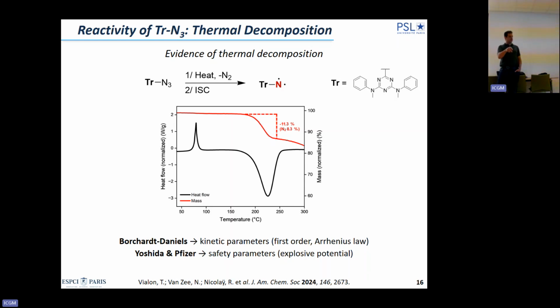And here, if you do this carefully, and this is well documented, has been done a lot, doing it at different temperature, different composition, you can access the kinetic parameter, you can access the enthalpy of decomposition, you can access the order of the reaction, and you can assess if the molecule is explosive or not, and above which temperature you should not keep it on your shelf for a prolonged period of time. In our case, it's above 60 degrees Celsius, so it is safe to handle, but I really don't want to provide a bad message.